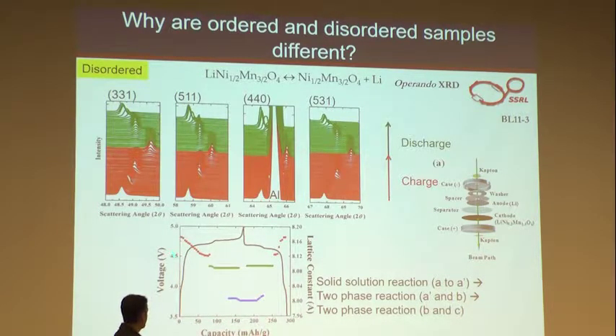That's the electrochemical curve that I was talking to you about. So whenever you see a battery paper, you'll see curves like that. These are just plots of the free energy with composition. And so this is the amount of electrons that are being removed when you go up, and when you come down is the amount of electrons that are put back in. Okay? The shape of the curve depends on the shape of the free energy curves for that compositional space. When you're going from lithium 1 to lithium 0, what phase is formed will determine this curve.